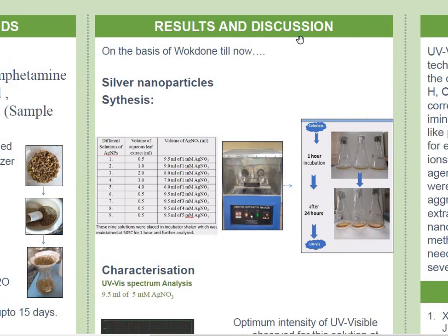Now coming on to the results and discussion part. Silver nanoparticles were synthesized using several volumes of leaf extract and several volumes and concentrations of AgNO3. So this is the table. Then these two solutions were mixed and kept in an incubator shaker for 1 hour at 50 degrees Celsius.